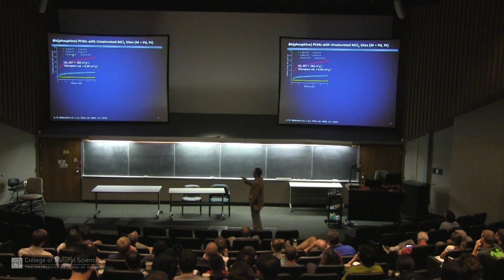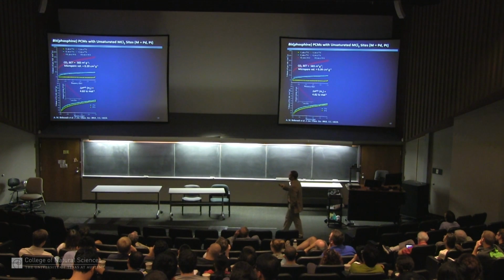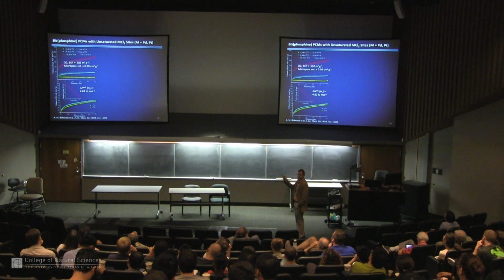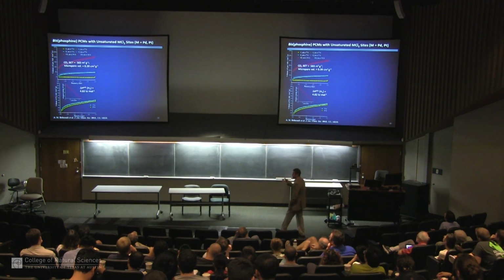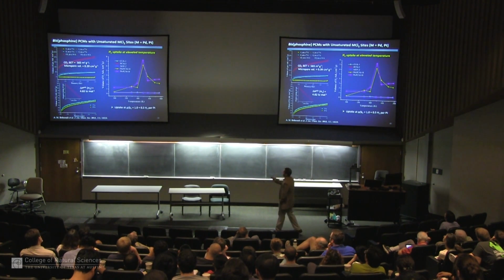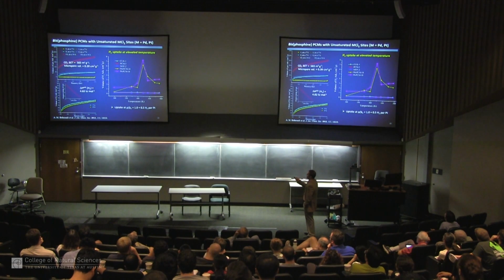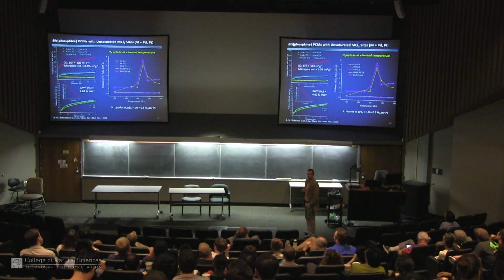When we look at the material, it has a high surface area. We do gas adsorption to measure the surface areas. This has a decent surface area that means it's accessible on the inside of the material. At low temperature, if you're looking for catalytic properties, nothing is really happening, but this is a cryogenic temperature. And that's not necessarily so surprising because normally most catalytic reactions on organometallic species will run at higher temperatures. But what we did find, to our pleasant surprise, was that at higher temperatures, actually 150 degrees, we start to get H2 binding at the metal sites in the pores.